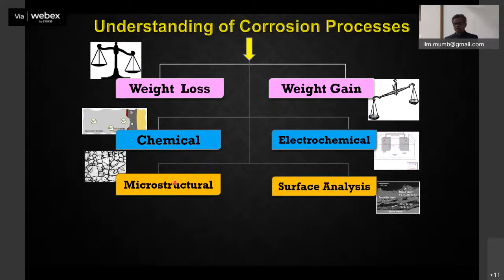Then came very strong metallurgical and surface modification analysis, where the microstructural effect was given, the structure property relationship. What is the microstructure? You take a stainless steel, there is a welding in your group, there is a delta ferrite coming in. That will have a problem. Otherwise, you heat treat it, it gets sensitized, it forms chromium carbide in the grain boundary, and then it leads to chromium depletion. So it depends on the microstructural condition, depending on the surface layer.